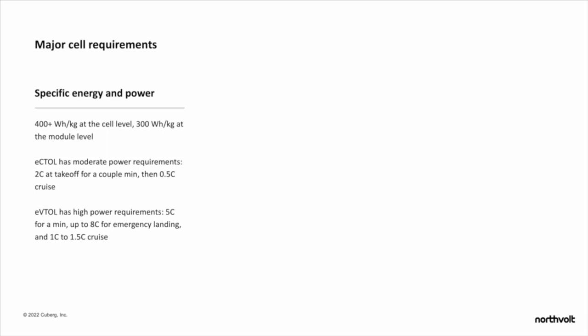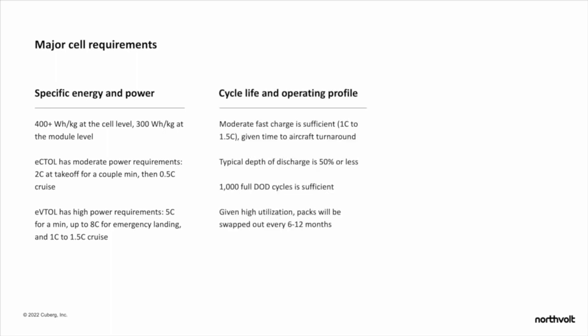But the cells that are designed for such high power with lithium ion end up having specific energy of 200 watt hours per kilogram or lower, even at the cell level, like 200, 220 watt hours per kilo for high power cells. So using a lithium metal chemistry allows you to use a high power cell design while still achieving really high specific energy. And it's really that combination of high energy and power that delivers what you need for air mobility.